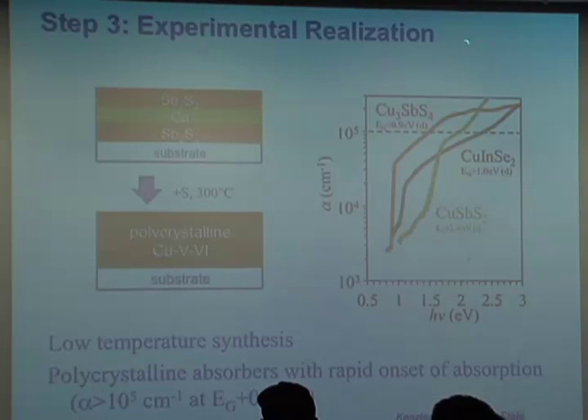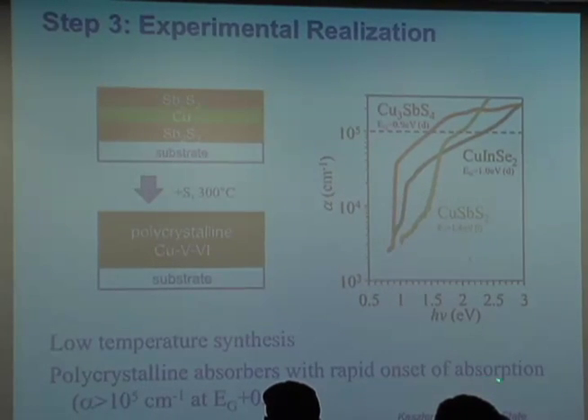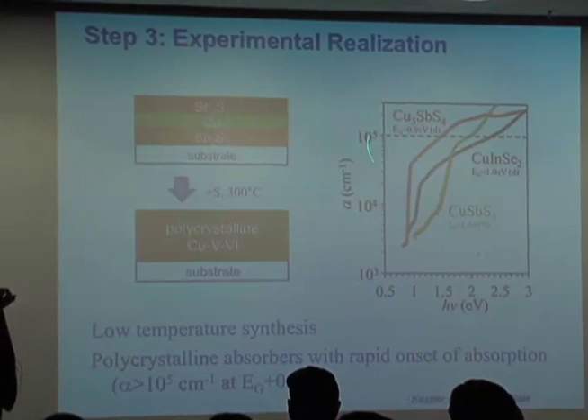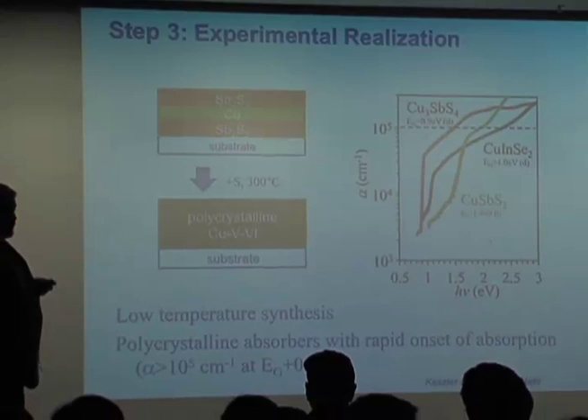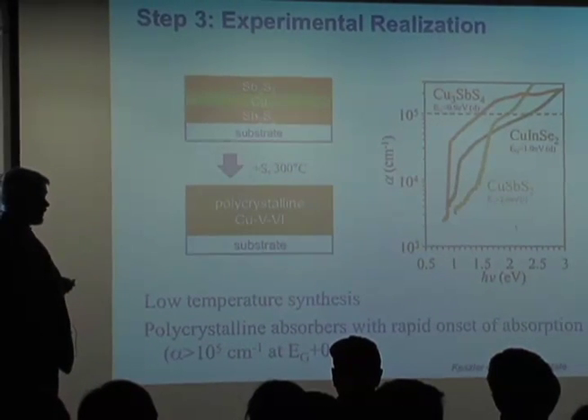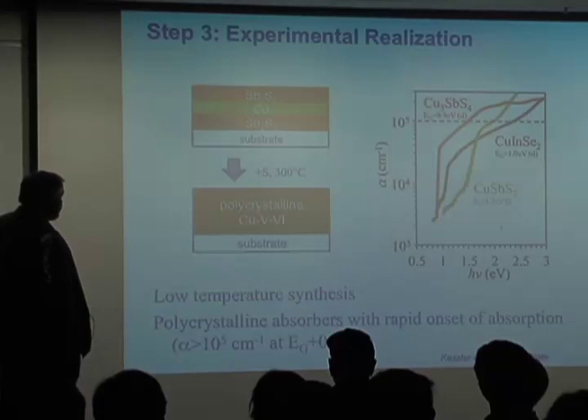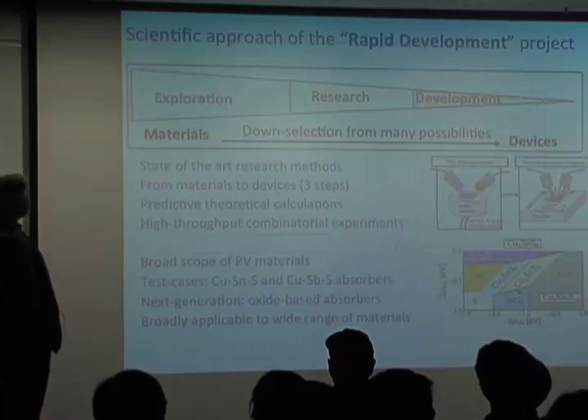And so now we're very interested in trying to realize some of those systems experimentally, and so at Oregon State they've been actually able to take layers of antimony sulfides and copper, anneal these systems into some polycrystalline systems, and see some of these absorption differences. And you can see that there's actually a rapid onset of absorption, and that some of these systems might be even superior to some of the copper indium selenide systems. Of course, we have to now worry about doping and some of the others. But this is a good way for us to start to explore the periodic table in a fairly quick way for some of the key properties and functionalities.